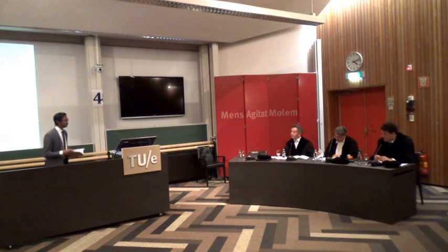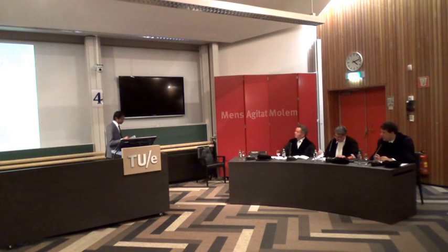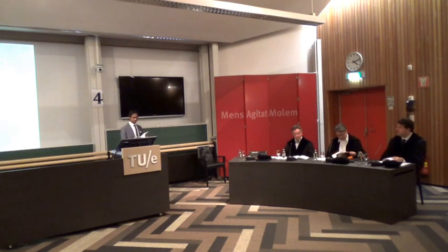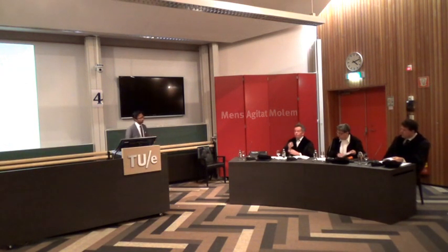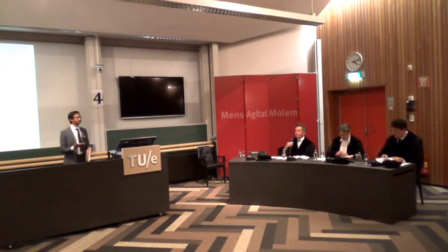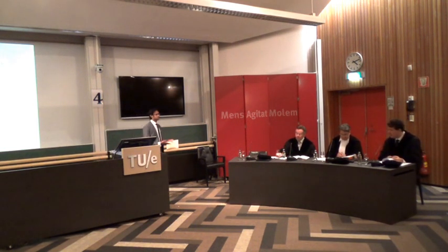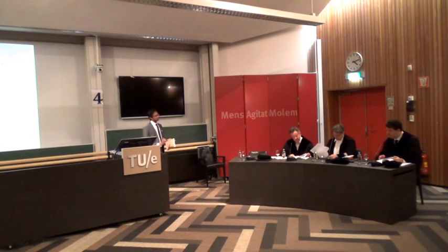Colleague opponent, thank you for your question. And yes, the aspect ratio plays a very important role, particularly in case of the composites which I'm preparing. For instance, in chapter 5, page number 139, I've shown the percolation curve processed by different methods. And here the aspect ratio is 137, I believe, roughly 140. Of course, if I use a different carbon nanotube which has a higher aspect ratio, the percolation threshold is going to decrease. But if I'm using a smaller aspect ratio, it is going to increase. That is just specifically based on aspect ratio.